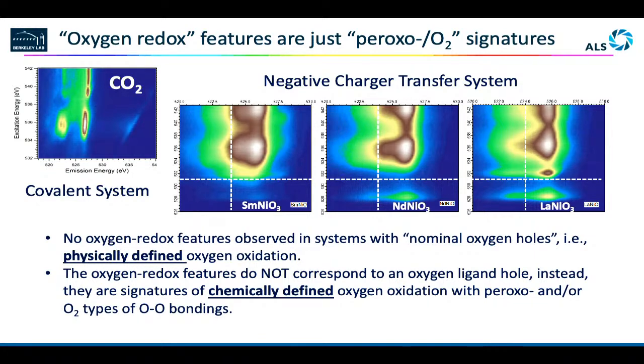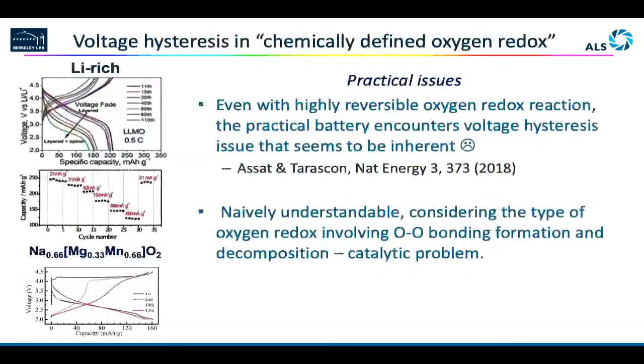So we do not see it if it's not a chemically defined oxidized oxygen. And again, those chemically defined oxidized oxygen with O-O bonding formation seem to give us an inherent problem with voltage hysteresis. This is just a review in Nature Energy, I think from Professor Tarascon's group, specifically talking about this theme: the killing factor of this kind of oxygen redox is the hysteresis of the voltage, meaning there is either a thermodynamic or a kinetic issue there. It was funny, last night there was a new paper coming out in Nature Energy, specifically on the topic of trying to solve the voltage decay in these lithium-rich compounds.